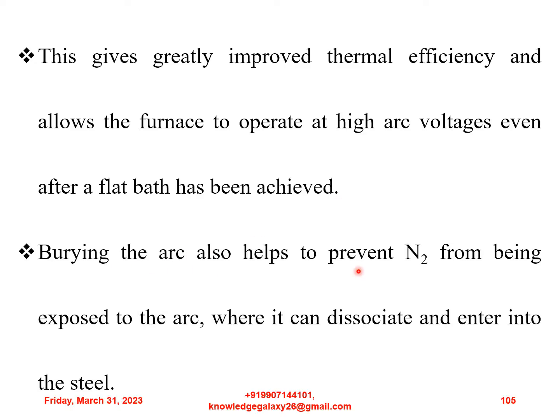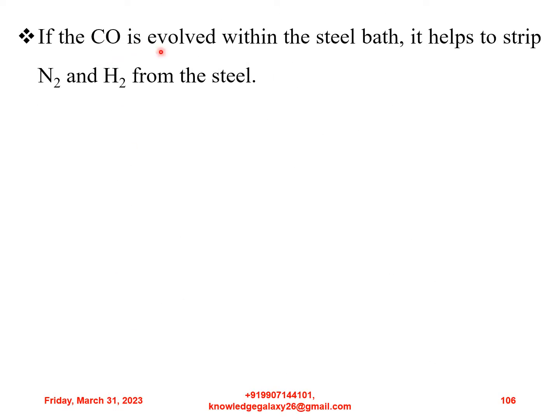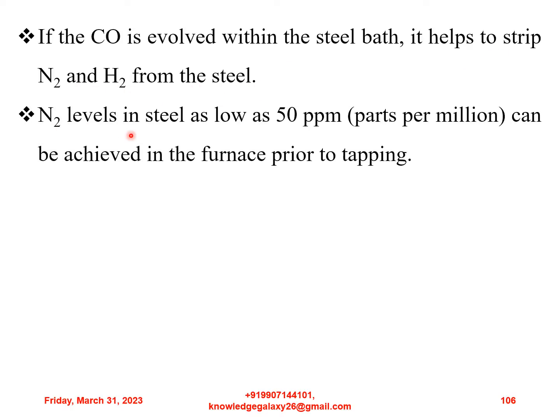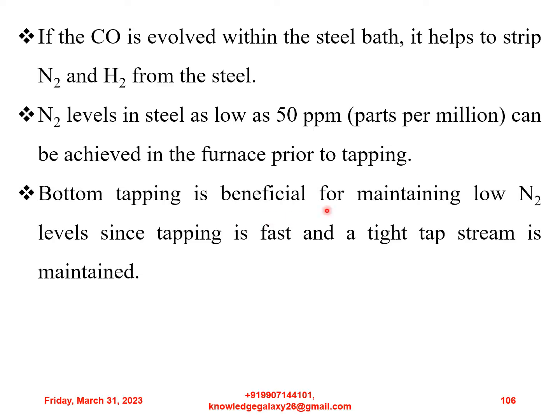Burying the arc also helps to prevent nitrogen from being exposed to the arc where it can dissociate and enter into the steel. If the carbon monoxide is evolved within the steel bath, it helps to strip nitrogen and hydrogen from the steel. Nitrogen levels in steel as low as 50 ppm, that is parts per million, can be achieved in the furnace prior to tapping.